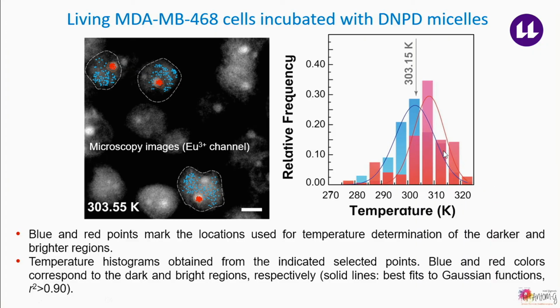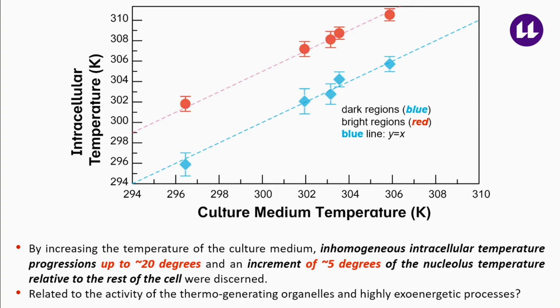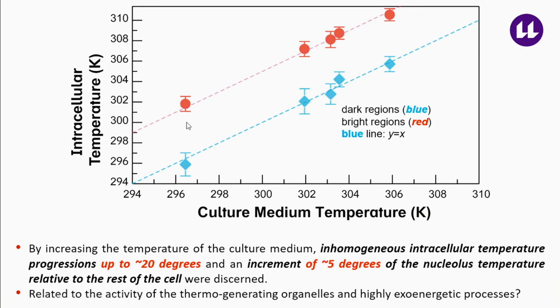The distribution has more or less the same full width at half maximum as the blue dots, but the temperature is higher, okay? We were able to localize the micelles in the nucleolus of the cell, and our proposal is that these red points represent the temperature of the nucleolus, which is around 5 degrees higher than the temperature of the rest of the cell.